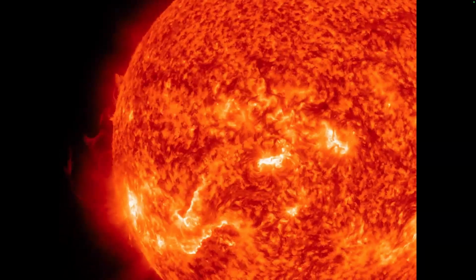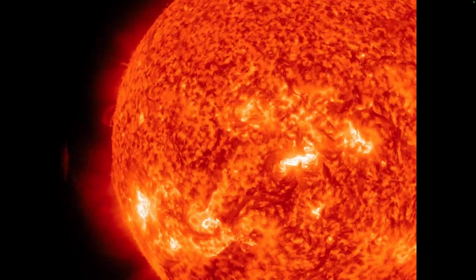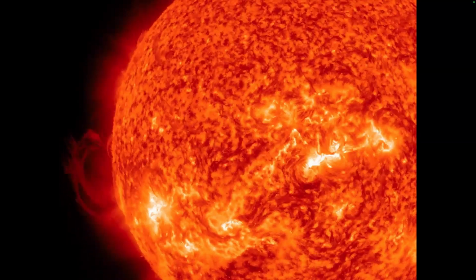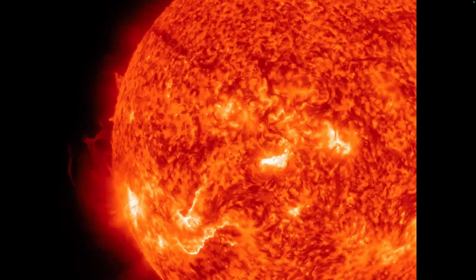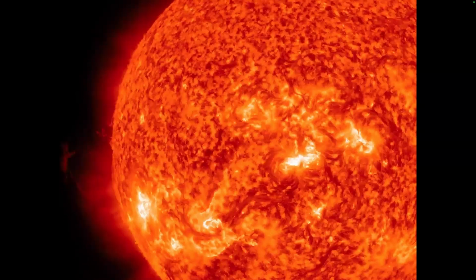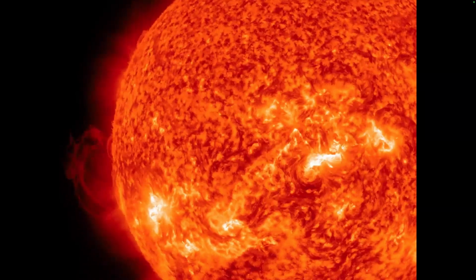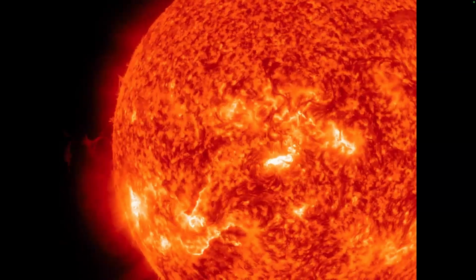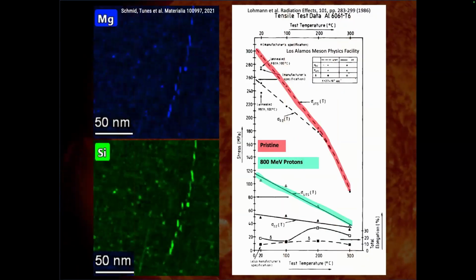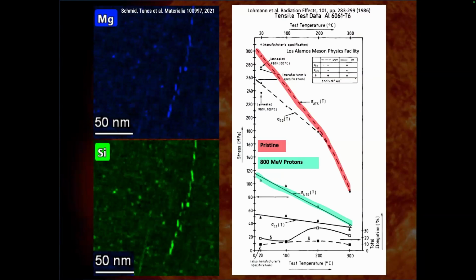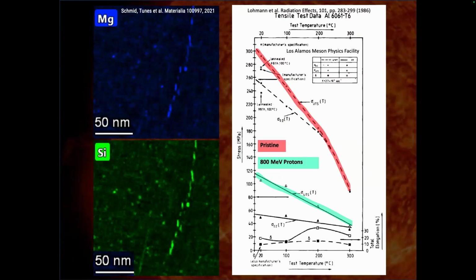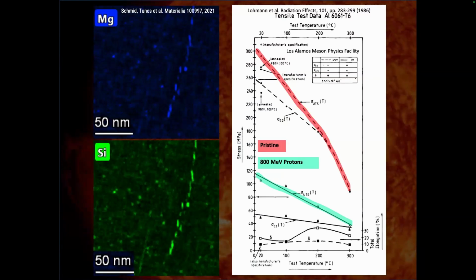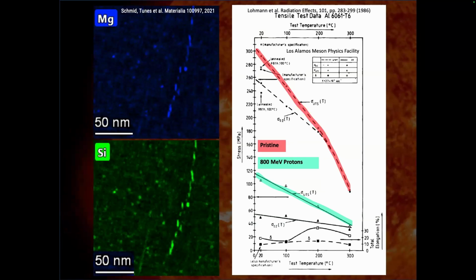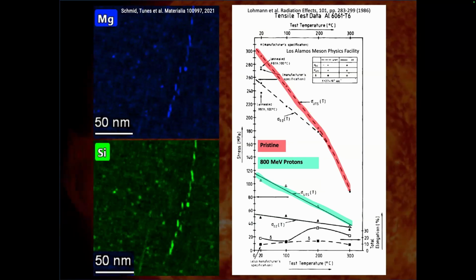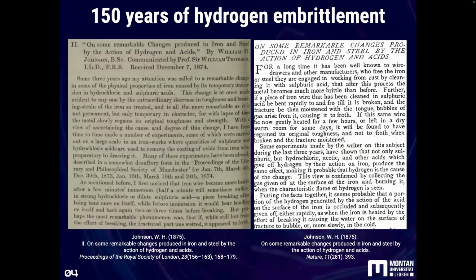In space, we have the sun, and the sun is constantly emitting hydrogen proton ions towards the Earth. And these protons impact the aluminum case of satellites and spacecraft, and it causes a little bit of hydrogen embrittlement as well. But the major impact here is when the proton impacts the aluminum, it dissolves the precipitates, and then you have a decrease in the mechanical properties quite significantly. I'm trying to understand if there is a space-related hydrogen embrittlement.